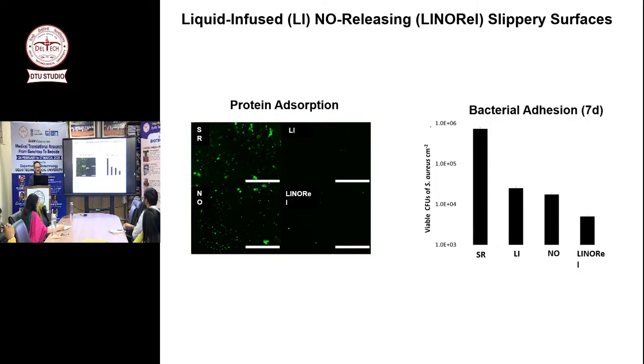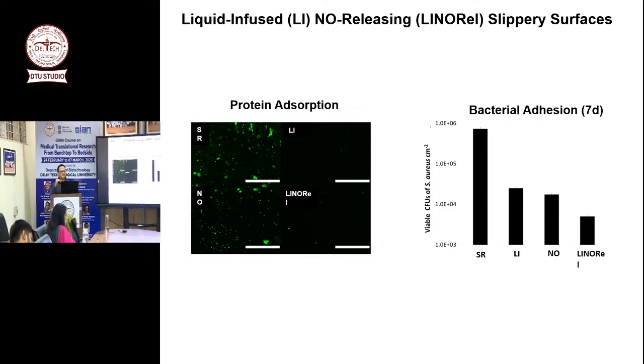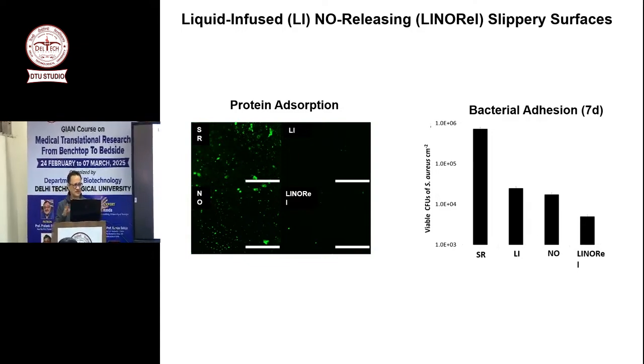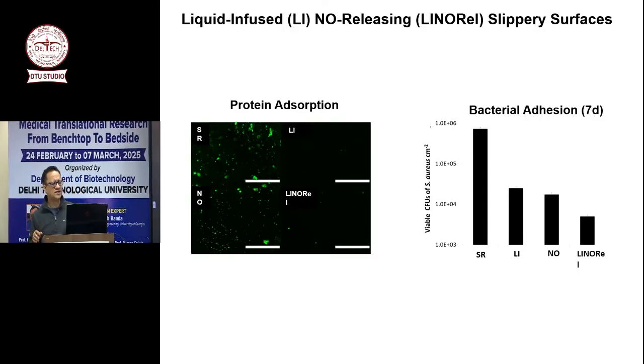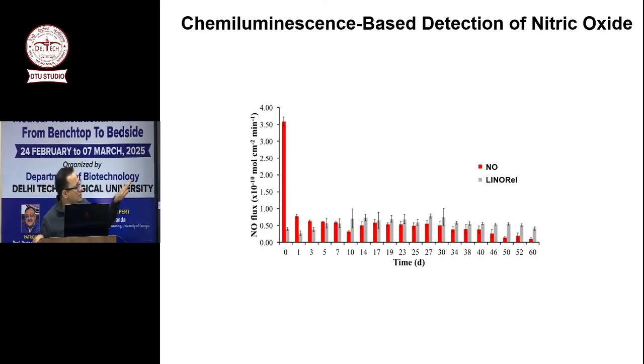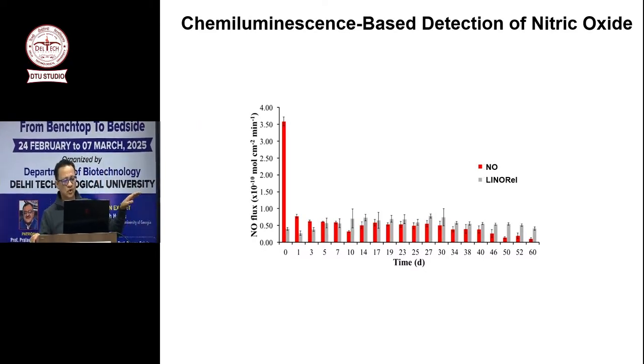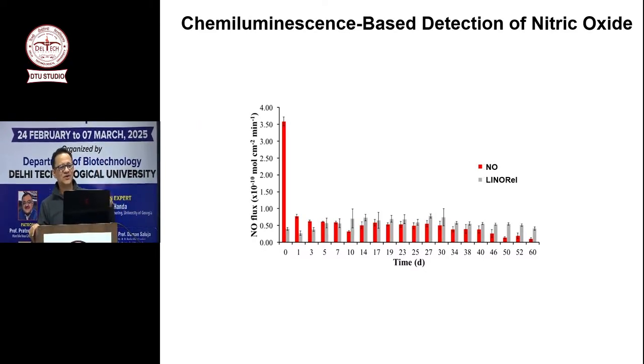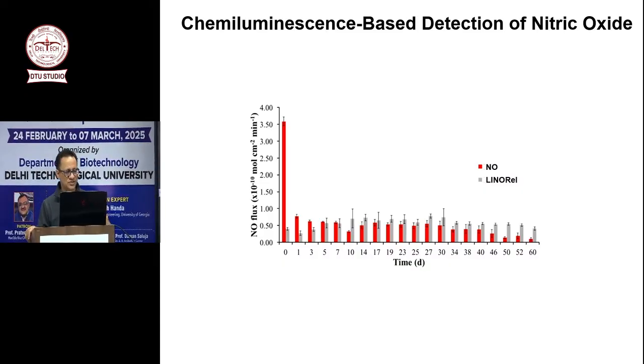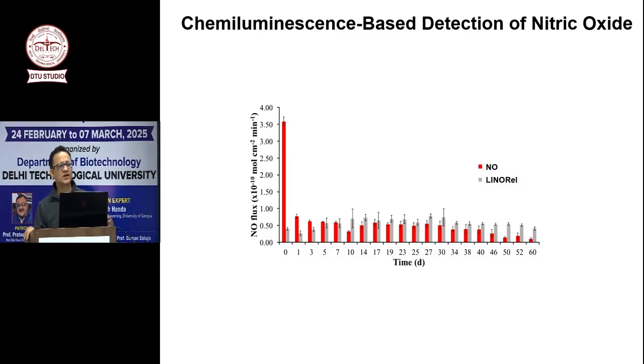We also did a 7-day bioreactor study where we showed that for Staph aureus, the combination of LINORel was significantly better than only liquid infused or only NO by themselves. We measured NO release and found that our NO release is pretty consistent over a 60-day period, whether only NO or NO plus liquid infusion. So liquid infusion is not hurting NO release. Of course, that's what we want, right?